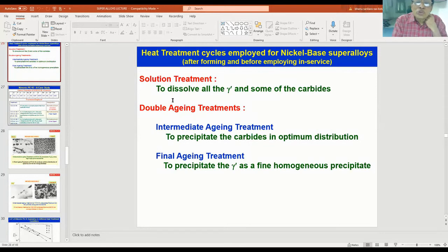The treatments subsequently given to the superalloys after solution treatment are double aging or triple aging treatments. If you are employing double aging treatments, one is called intermediate aging treatment and another is called final aging treatment. The goal of intermediate aging treatment is to precipitate the carbides in optimum distribution on the grain boundaries. This is required for imparting creep resistance at elevated temperatures. The final aging treatment is to precipitate your strengthening phases, gamma prime and gamma double prime, as a very fine precipitate, homogeneously distributed in the matrix.